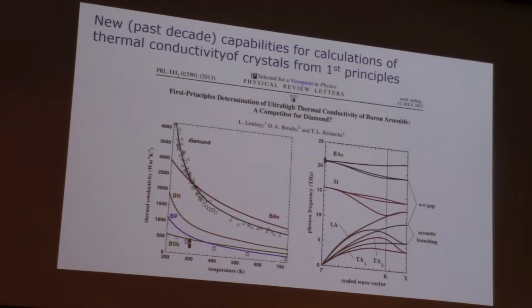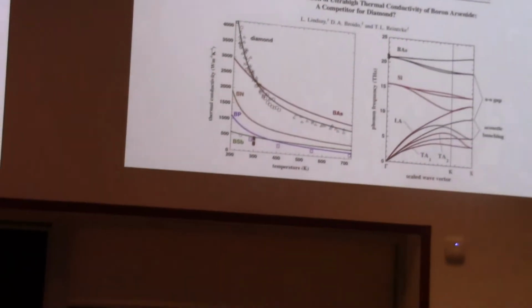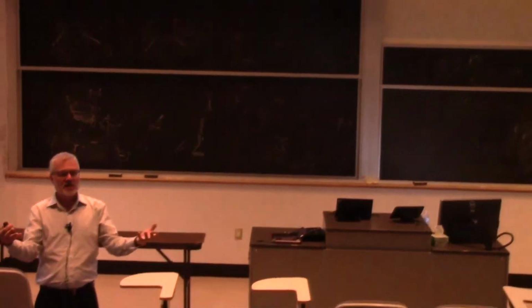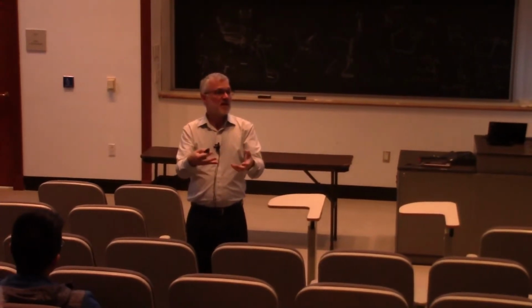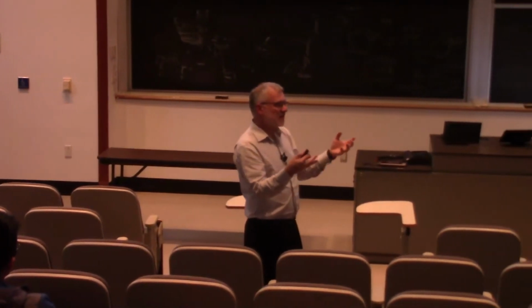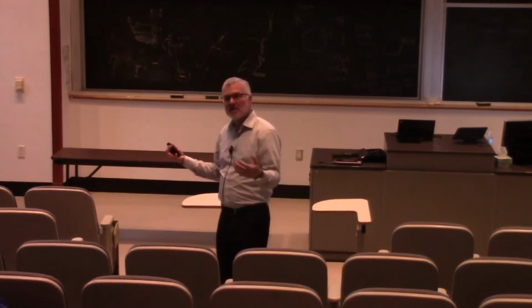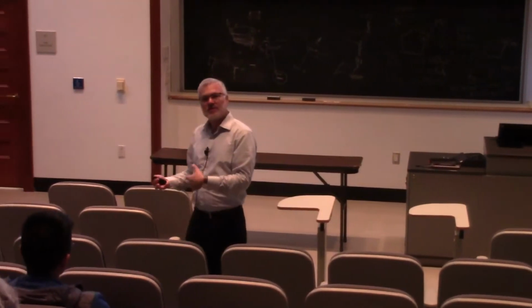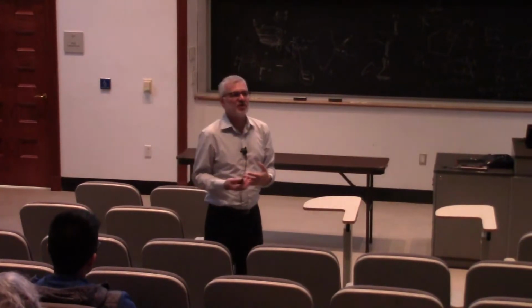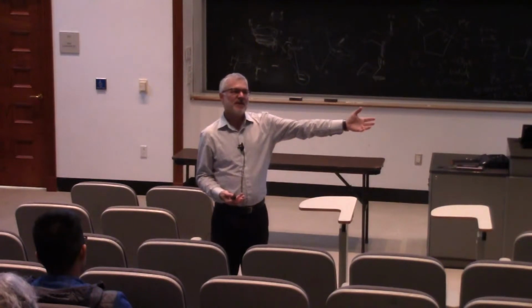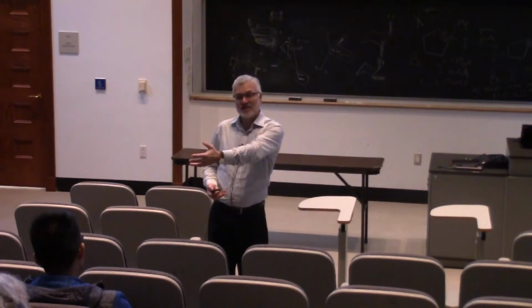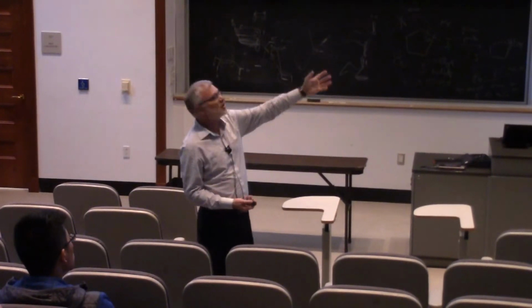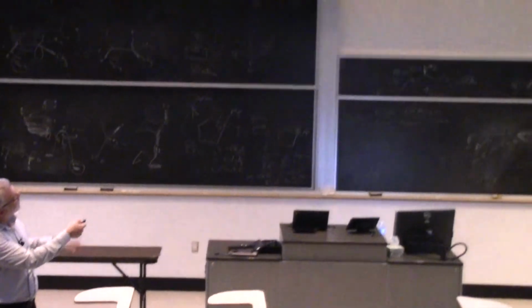So there are a couple points about this I want to leave you with. One is this is a paper from 2013, but actually the whole subject starts somewhat before that, and it's really an impressive advance in theory. So theorists, by combining density functional theory, so computational techniques, quantum mechanical based, to calculate the force constants of atoms, as well as their nonlinear force constants, so their anharmonicities, and then using that information to solve transport equations, the Peierls-Boltzmann transport equation, which was first written down in the 30s, but had never been solved quantitatively until quite recently, can make predictions. So this is just one example. This is from David Broido, who I think would be considered really the lead of this group.